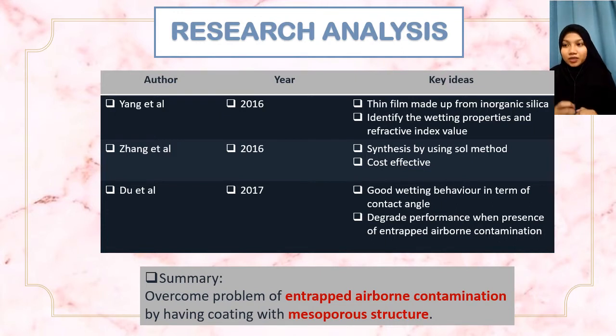Their research obtained good wetting behavior, with a contact angle of less than 90 degrees. However, the hydrophilic properties degrade when there is airborne contamination in the coating. So, as a summary, this current research aims to overcome the problem of entrapped airborne contamination in the coating by having a coating with a mesoporous structure.